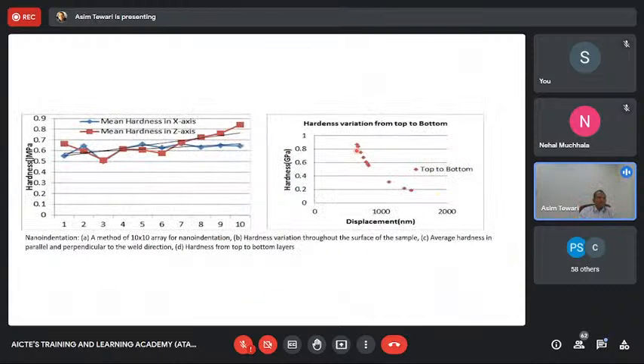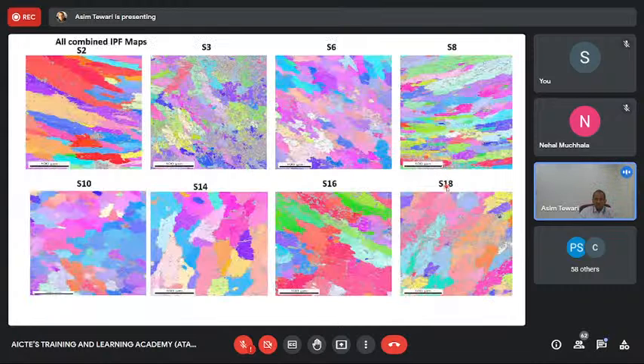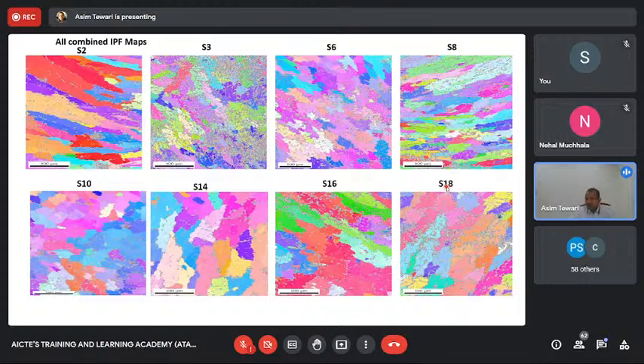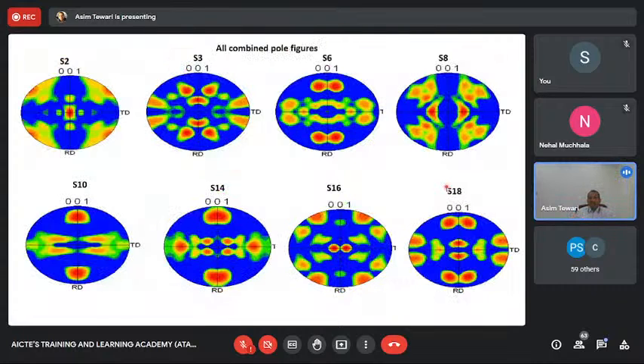You can also see variation in hardness. So when you measure the properties, you see a variation in properties. Texture is varying a lot depending upon where you are adding. In some parts, the grains are equiaxed. In some parts, they are very elongated. You can have the macro texture looked at, which is the crystallographic orientations, which may not be something which you all understand.